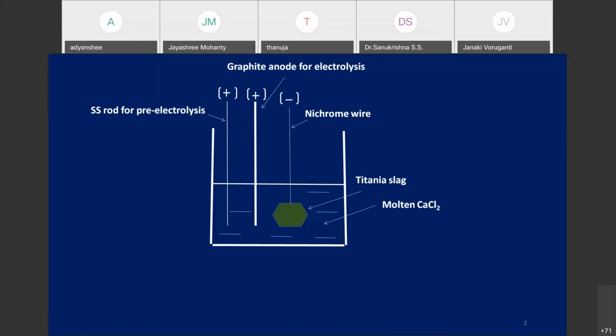Upon application of the potential, how much? During pre-electrolysis, we usually apply a potential of 2 volts. So what will happen in this case? If any moisture and any redox active materials are there, they are removed by this process. So first you carry out the pre-electrolysis, and when you carry it out, first you heat the calcium chloride.